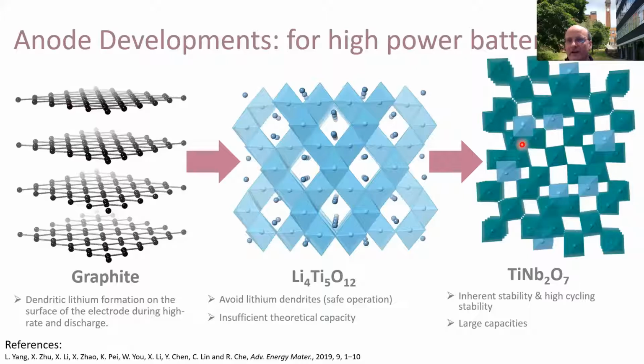And as I say, there's a whole host. Some give you higher energy density and might give you 10 minutes charging. Others might give you slightly lower, but may give you 3 minutes charging. So again, you can choose a material that suits your application. Do you want really high energy, relatively rapid charge, or do you really want that rapid charge but can cope with a little bit less energy?